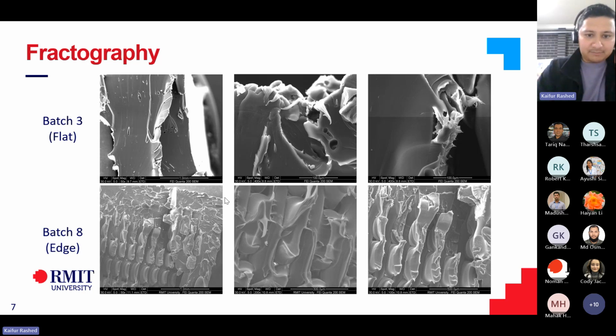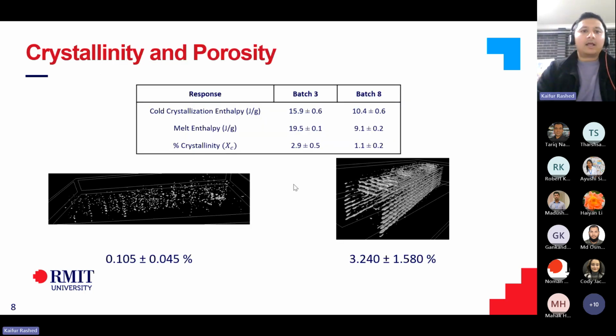But then again, the question comes, why does that happen? So then I looked at crystallinity, because crystallinity is one of the reasons why this could happen. If there's a significant difference in crystallinity between the 2 batches, then that could cause differences in mechanical properties. I looked at crystallinity, and as you can see, between batch 3 and batch 8, the percentage crystallinity doesn't vary significantly. It's between 2.9 and 1.1. So both are essentially mostly amorphous or pseudoamorphous.